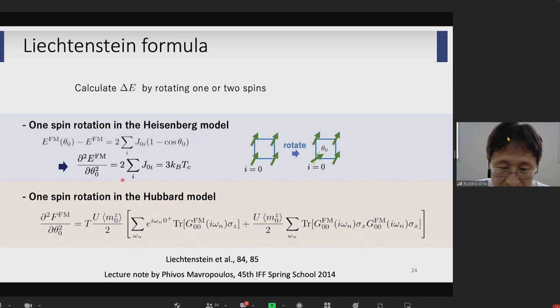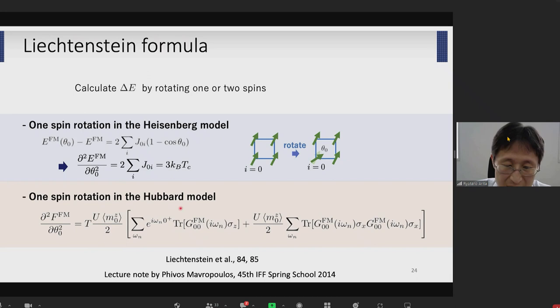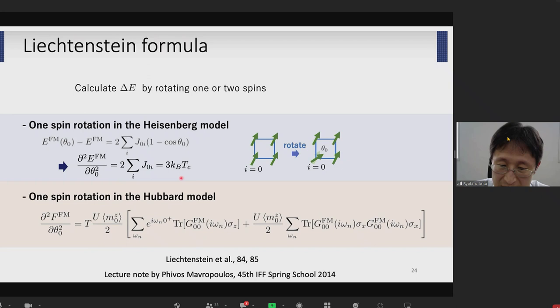We can also consider rotating one spin, choosing one spin and rotating its direction. By looking at the change in total energy, we have information on the summation of J0i — the interaction between a chosen site and all others. This quantity is important for a rough estimate of transition temperature. By mean field theory we can derive that if we have the sum of J0i, we get a rough estimate of transition temperatures: Curie temperature, Néel temperature, or critical temperature. This quantity J0 can be obtained if we have information on the Green's function.